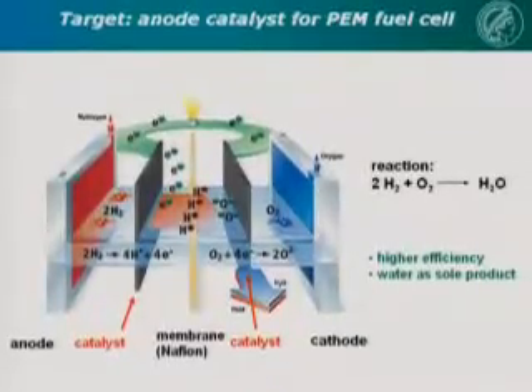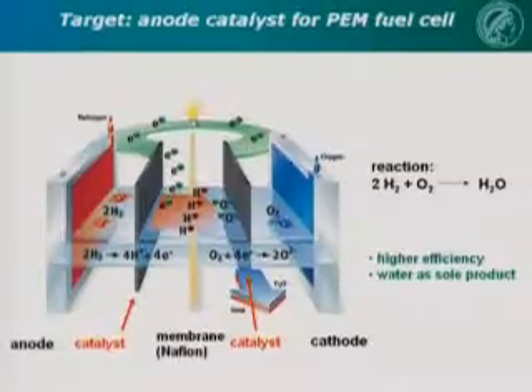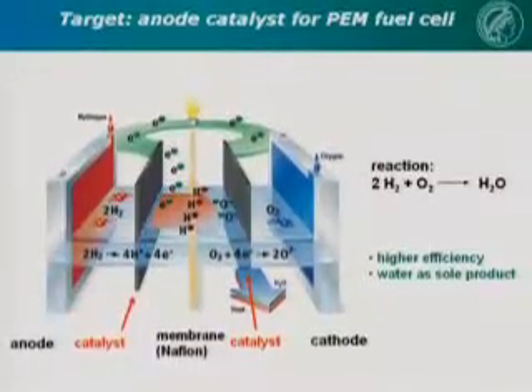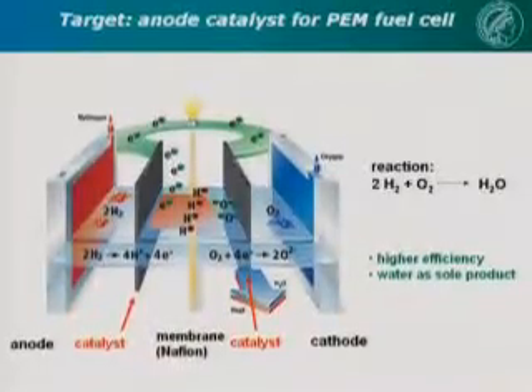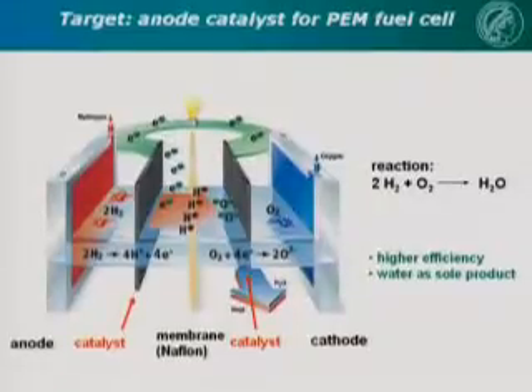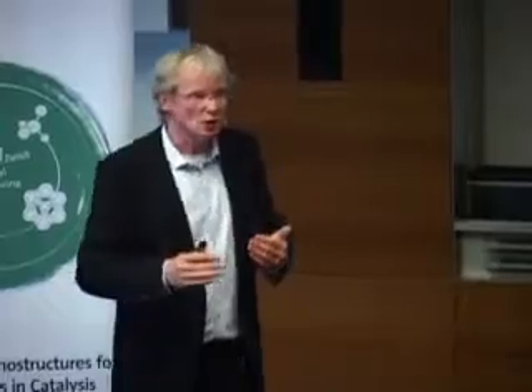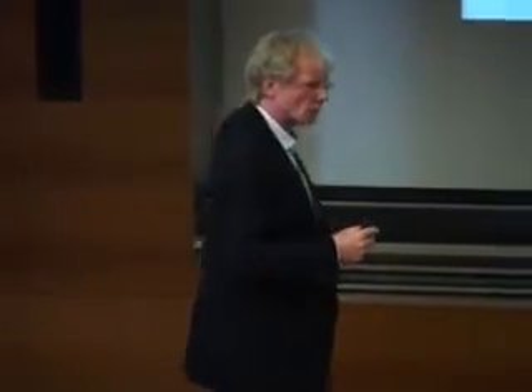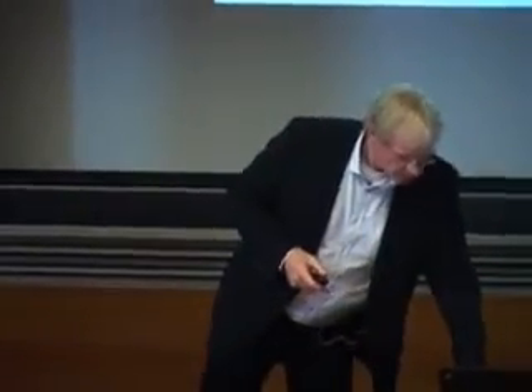And we decouple the reaction. We need platinum typically on carbon catalyst, and this is the catalyst we want to look at. On the hydrogen side, the hydrogen oxidation catalyst, the anode catalyst. One of the crucial problems in these catalysts for commercial applications is actually corrosion of the carbon support and loss of activity. These catalysts are not long-term stable. This is one of the big problems which is often neglected.